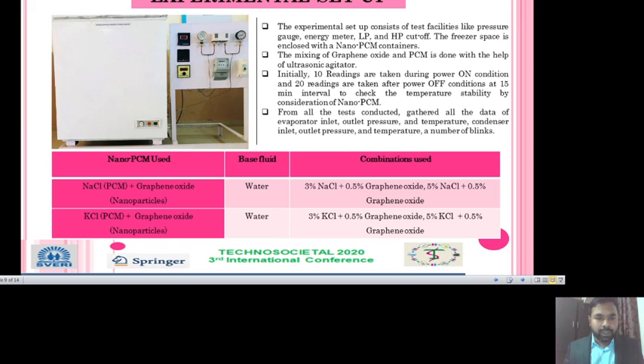Similarly, these are the combinations. There are a total of 4 combinations. In the first row there are 2 combinations. Initially we took 3% NaCl as the Nano PCM and 0.5% graphene oxide nanoparticle, with water as a base material. In the second case we used 5% NaCl and 0.5% graphene oxide nanoparticle along with water as a base material.